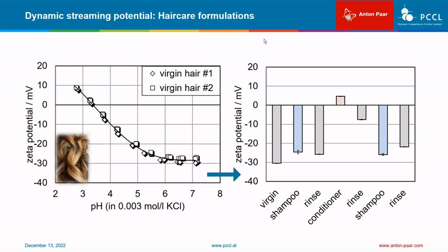Application of a conditioner reverses the sign of the charge from negative to positive. Rinsing again with buffer solution removes an excess of the conditioner and leaves the hair slightly negatively charged. Application of shampoo shows the same Zeta potential of the first treatment step, while the final rinse now shows that shampooing does not fully remove the cationic component of the conditioner. Due to the sensitivity of the Zeta potential, we do not assume a large surface concentration of conditioner remaining on the washed hair.